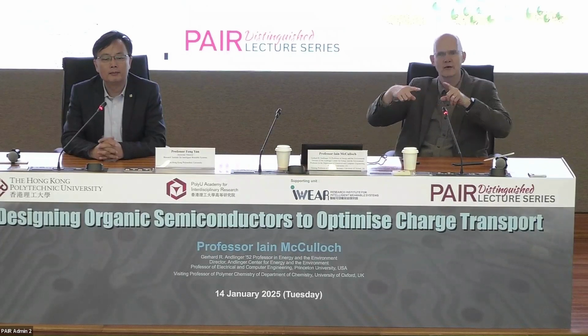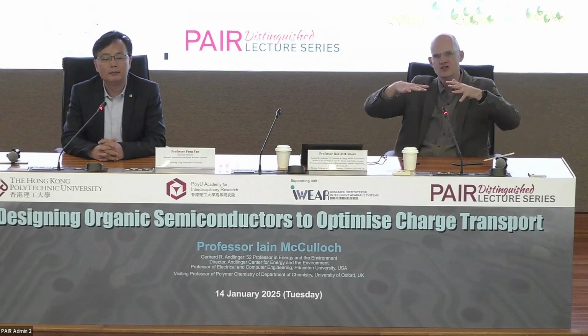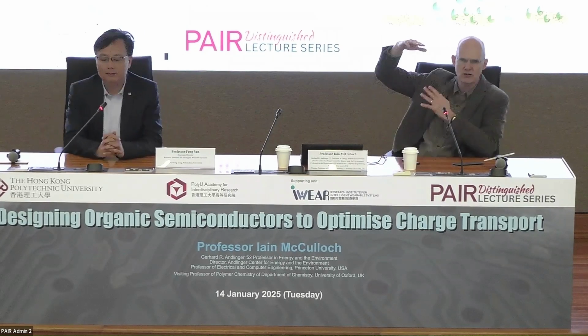If you think about that analogy, we can use it to design materials that have what we call non-covalent interactions along the backbone. And these non-covalent interactions create the superhighway, if you like. They reduce the amount of damping that's formed when you form a polaron. This is what we call in chemistry the reorganizational energy, and you can think about this in terms of Marcus theory. You could look at the extent of that, but having systems with low reorganizational energy helps in that regard. But that's the theory.